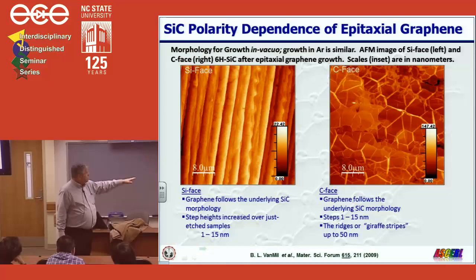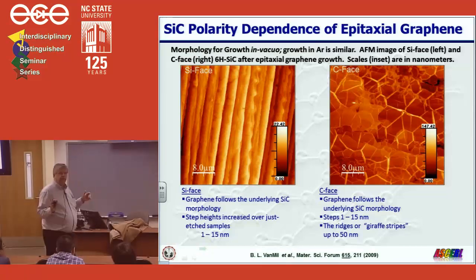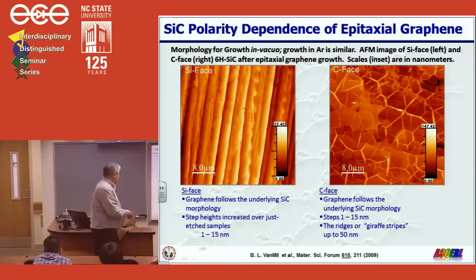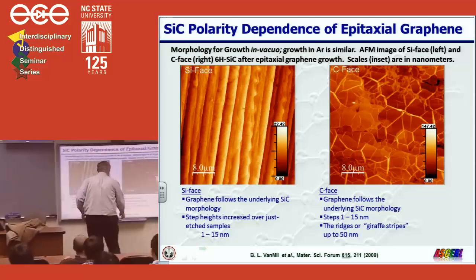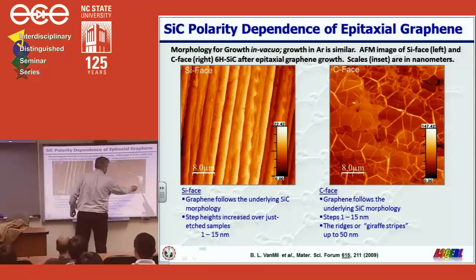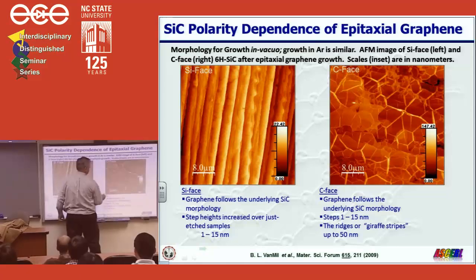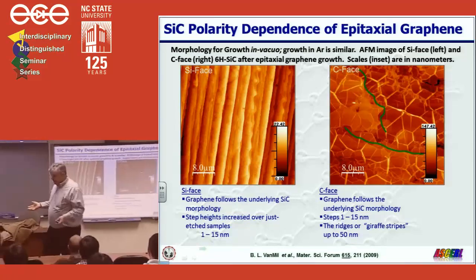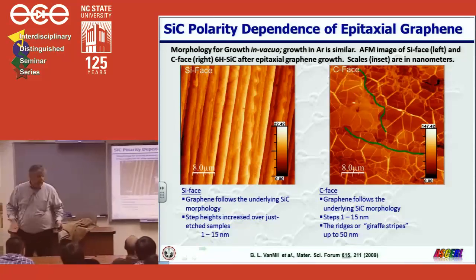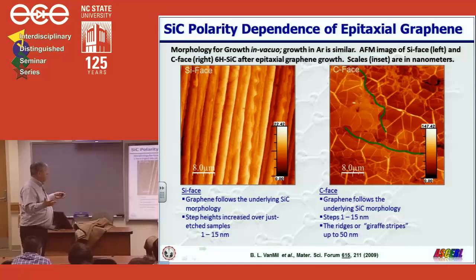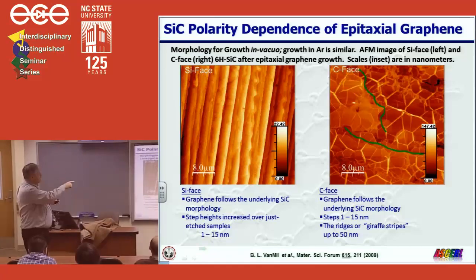On the right-hand side, morphology is extremely complex. If you look carefully, you can almost make out an image of a step that remains after the growth. Let's try green. You can see one there. Yeah, it looks like a vestige of one here. So it etches erratically, the steps are moving erratically, and you get actually a very thick film of graphene on top, and then you have all these ridges which look like those yellow lines.